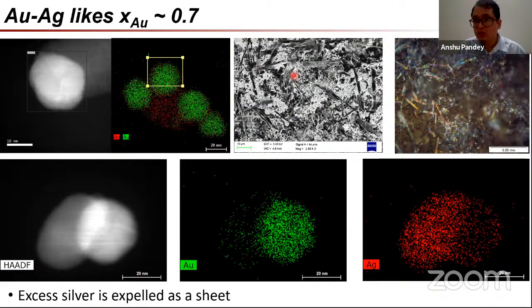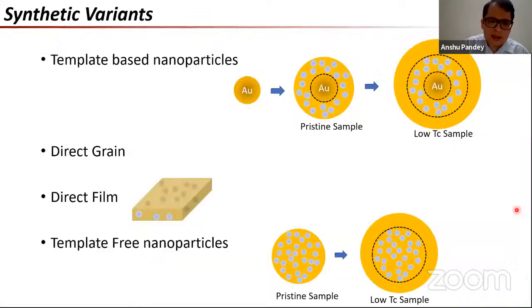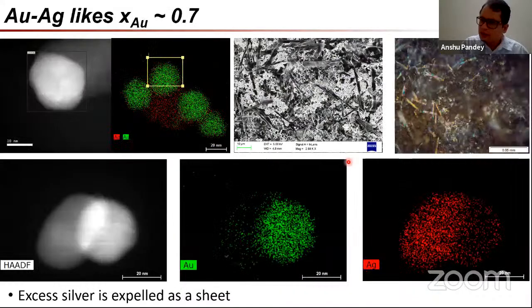This effect operates seemingly on all length scales. So if we make samples via different routes, for example, over here, and this is a direct film route, which I'll discuss in detail in my presentation a little later, we find that over the course of a few days, if there is excess silver present, material tries to expel these or forms these very unusual, quite iridescent to the eye looking sheets. And doing the elemental analysis of these sheets actually shows that these are in fact made of silver and not gold. They contain no gold, but in fact are pure silver. So it's actually extruding silver into the environment, trying desperately to return to a point zero. And these are happening not just on one type of sample, but rather across a few classes of samples.